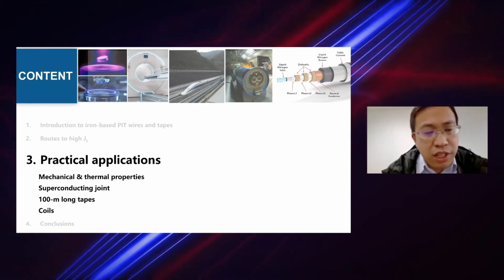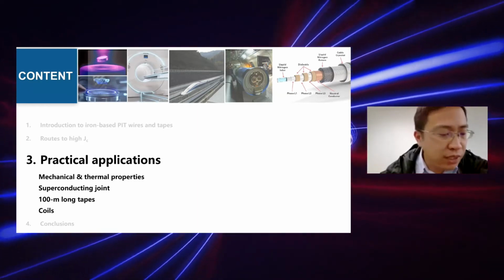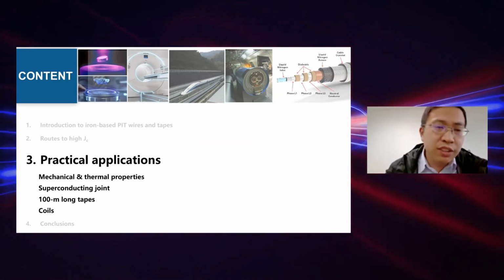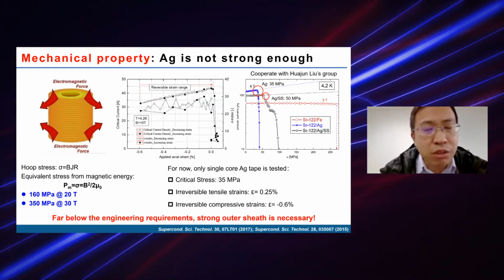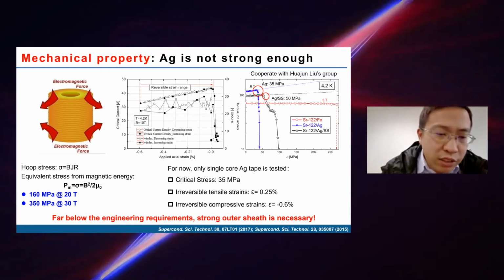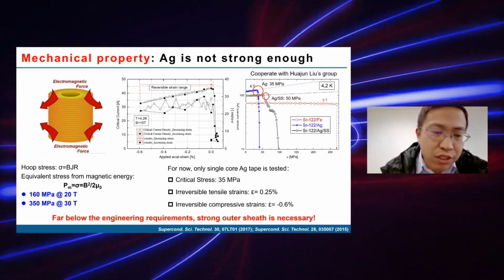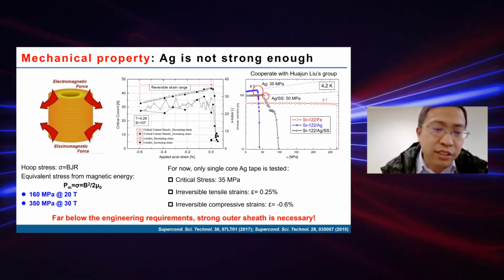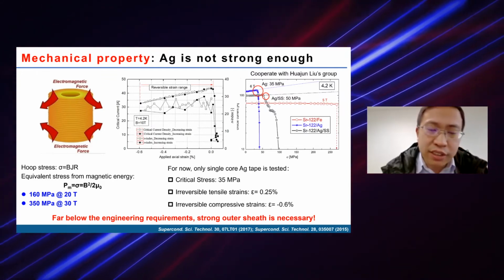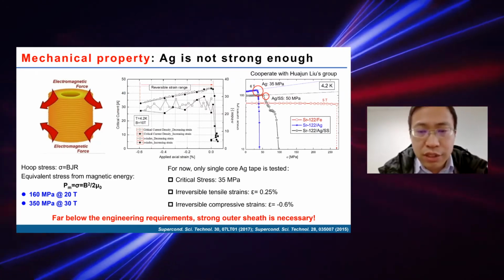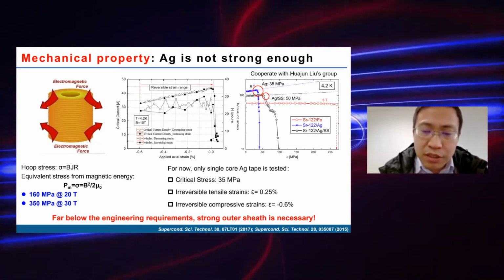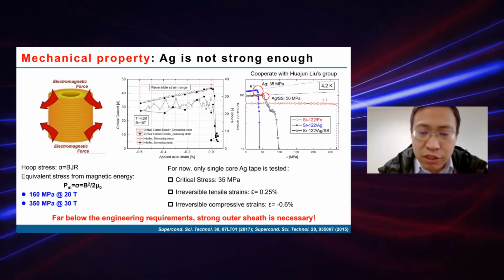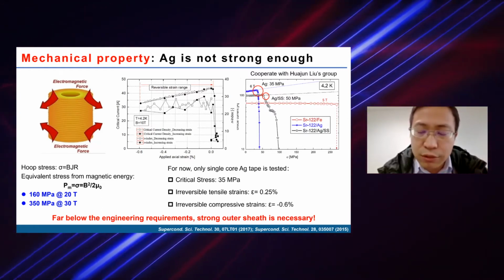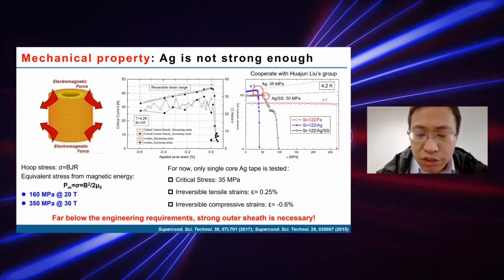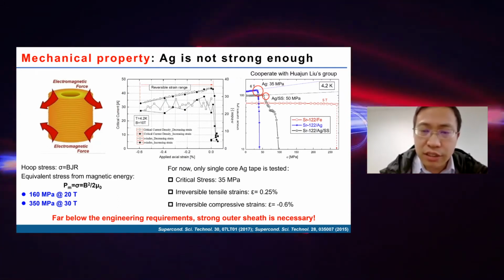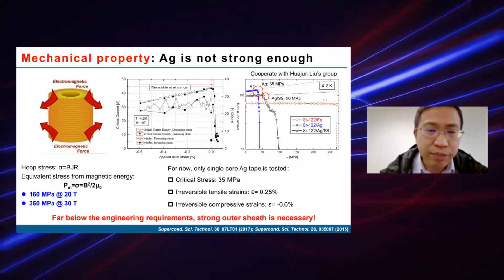And then I will talk about the recent applications of iron-based superconducting wires and tapes. The first property that must be considered is the mechanical properties. The equivalent stress from the magnetic energy is estimated to be 160 megapascals at 20 Tesla. However, silver is very soft. The critical stress is about 35 megapascals, and the reversible tensile strain is only 0.25%. So stronger outer sheaths are necessary in iron-based superconducting wires and tapes.